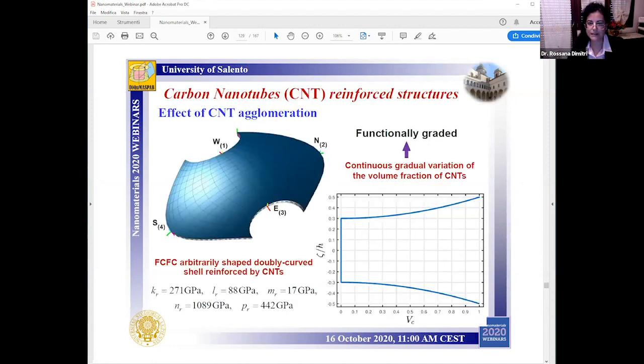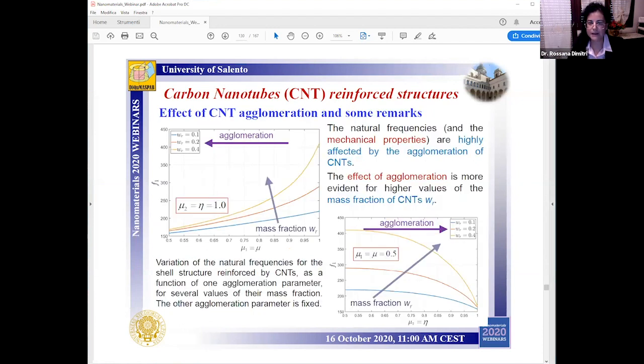And as a further example, we analyze the effect of the carbon nanotube agglomeration on the structural response for this kind of doubly curved shell reinforced by carbon nanotubes with a functionally graded variation of the volume fraction throughout the shell thickness, as visible in this plot. And here we just comment about the first natural frequency of the structure versus mu and eta.